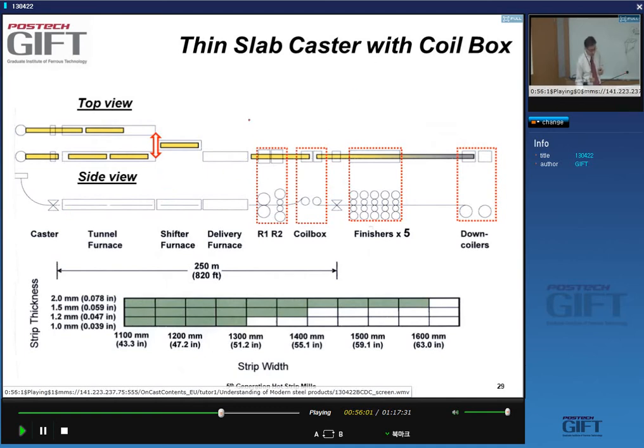Right, so this would be a possibility here. You cast, you can have, or not, depending on the situation, some tunnel furnaces, yes? You have a shifter furnace that will bring the bar that's ready to be rough rolled into line with the rougher stands. So here you have the roughers. They usually operate in tandem, so it's not a reversible mill. Then the strip goes into the coil box, and it's uncoiled when the finisher is available for rolling. Laminar cooling, down coiler. All right.